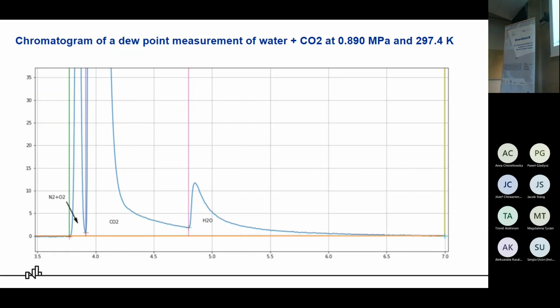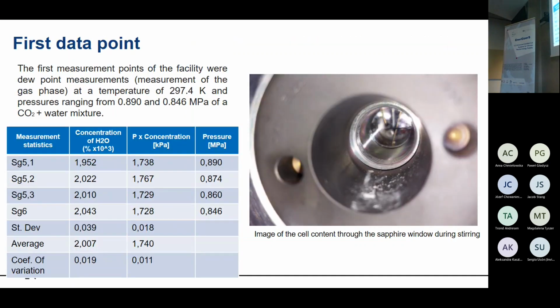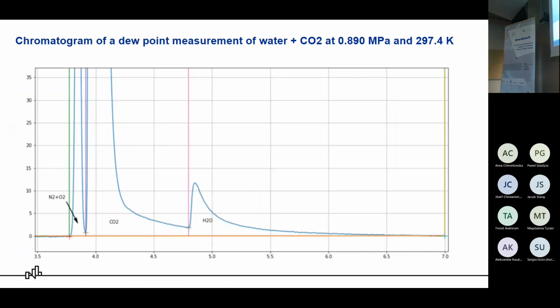And here is the chromatogram of dew point measurements. We have the CO2 peak and water peak, and from the area of these peaks, we can assume the mole fraction. So for this chromatogram, we have a 0.2% concentration of water in our mixture.